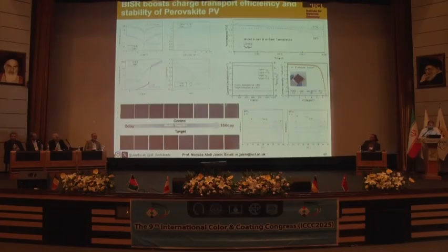You can see the SEM images over here, and it's significantly better in terms of the size of the grain and also in terms of the stability of the material. And obviously we made solar cells and we got over 24% efficiency. In terms of the stability, I think the quality is not great here, but you can see that the one without the 2D phase is degrading significantly over time after 150 days, but the one with the 2D phase, there is almost no change.